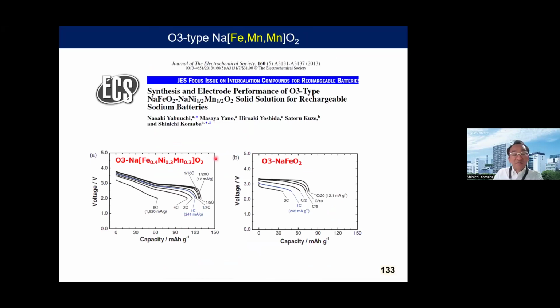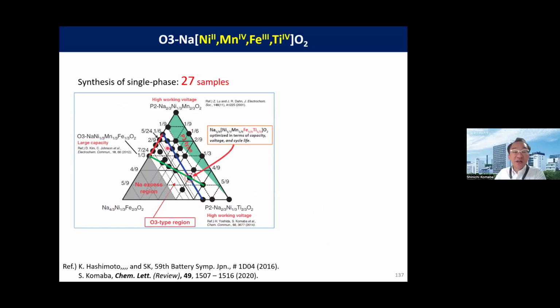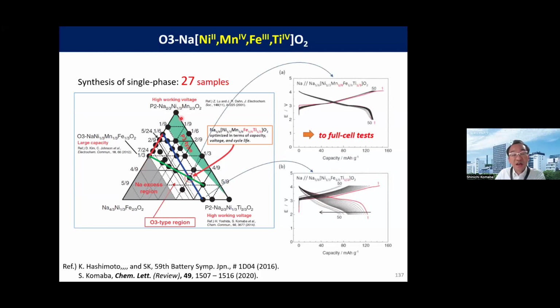And one typical, good candidate for practical use is the iron nickel manganese layered oxide. In the region below 4 volts, it has relatively high reversible capacity and a smooth charge-discharge reaction. And because it is an iron manganese-based material, it is considered to be one of the earth-abundant materials for sodium-ion batteries. And recently we tried to optimize the nickel manganese iron titanium layered oxide, and finally from this triangle phase diagram, this point should be optimal for reversibility and also working potential region.